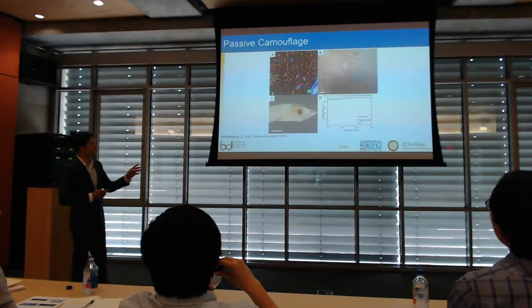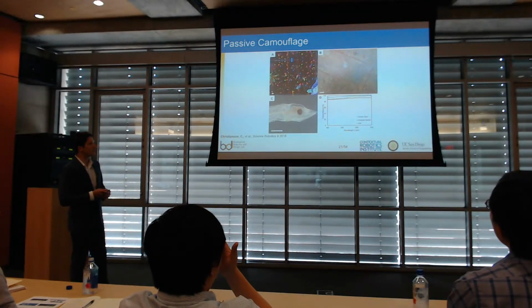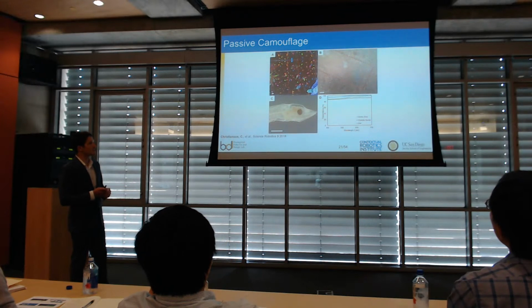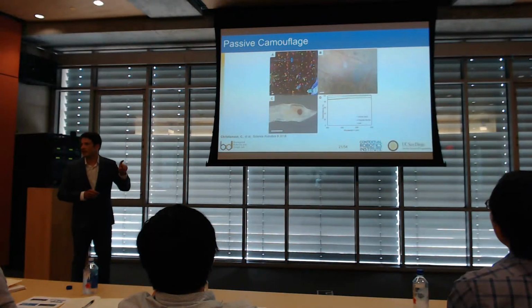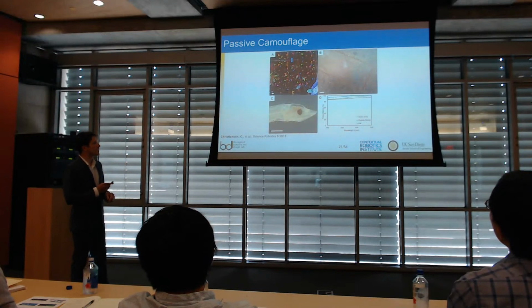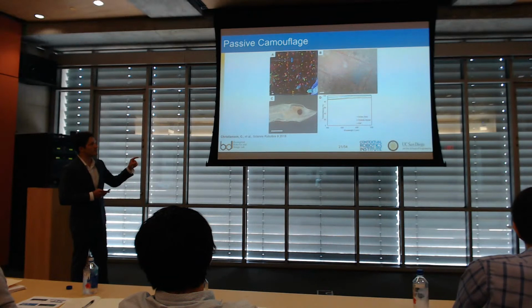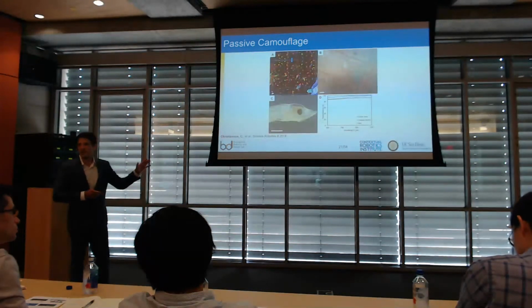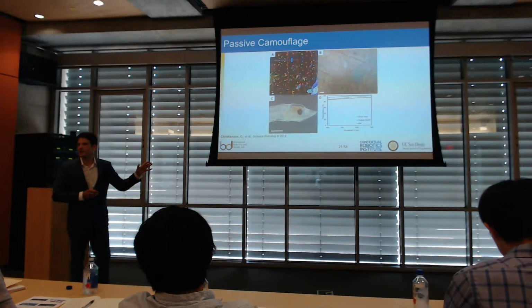This is the transmittance over the visible spectrum. And there's two different regions of the actuator. There's the active area, which is at the center of the actuator, and then there's the outside border that goes around the outside. And what we see is that the two different regions of the actuator bound the transmittance of the eel. So in other words, it's about as transparent as it can be.